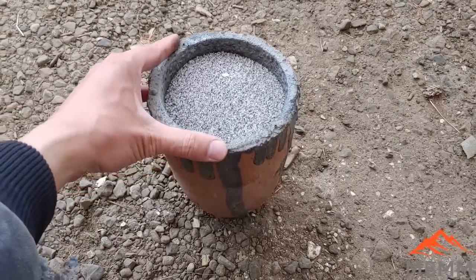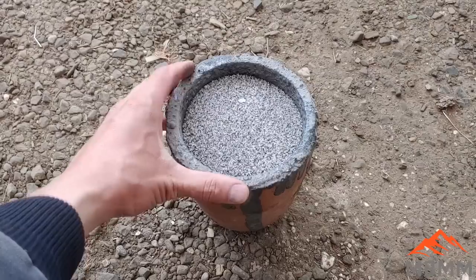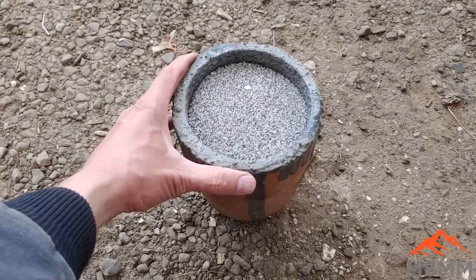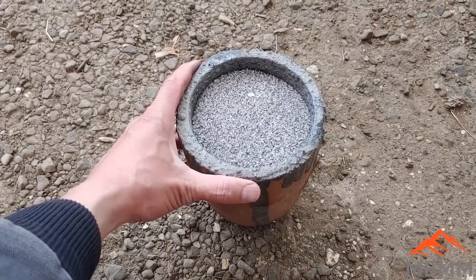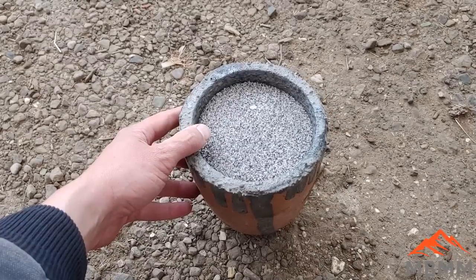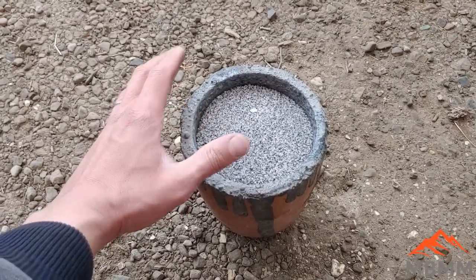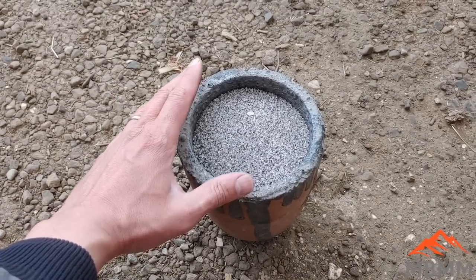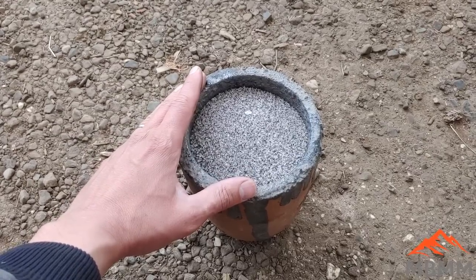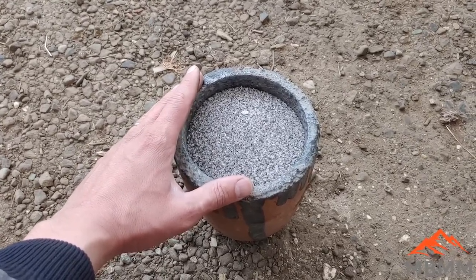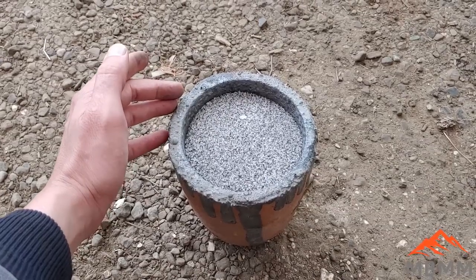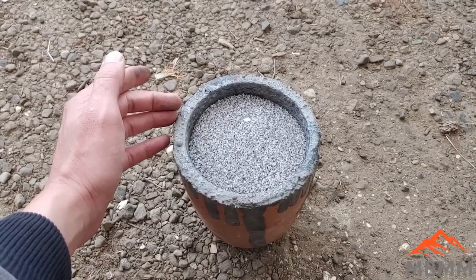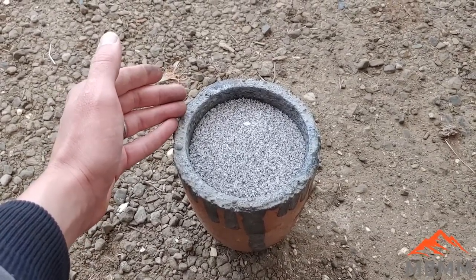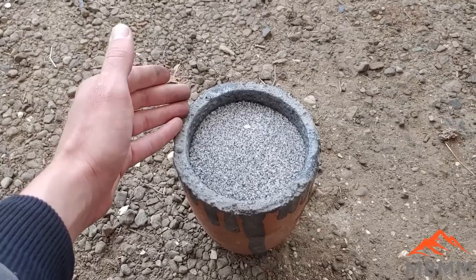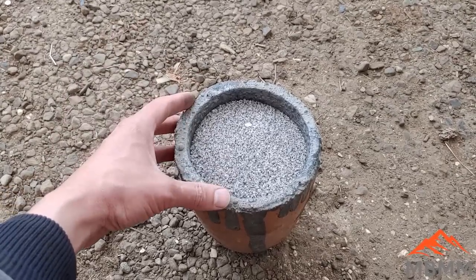All right, here's dried out material from the number 2 off the shaker table. And we ended up with 1,300 grams after it was dried. So I took that material and split it in half, so I have 650 grams of the number 2 here. I mixed it with 650 grams of borax, 650 grams of lye, and 325 grams of silica sand. So it's 1 part ore, 1 part borax, 1 part lye, and half a part silica.